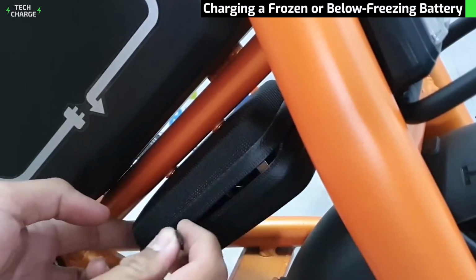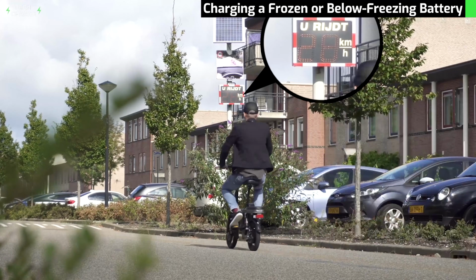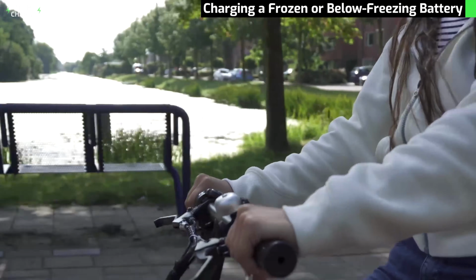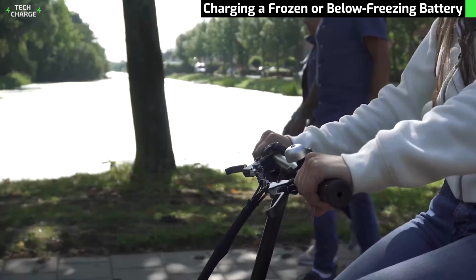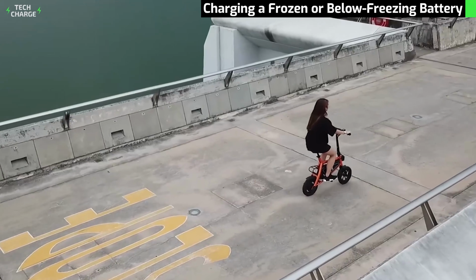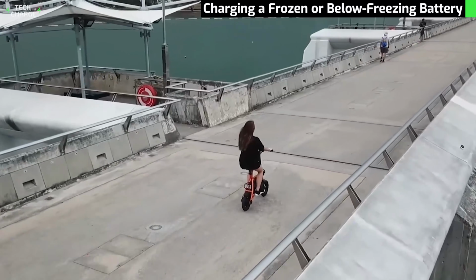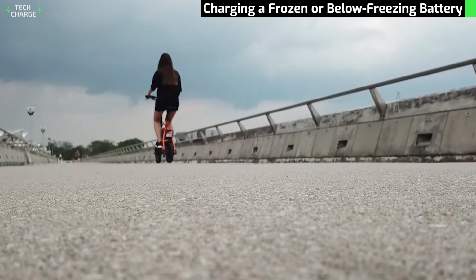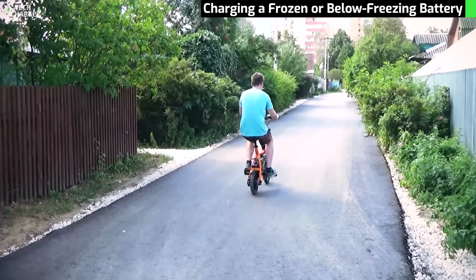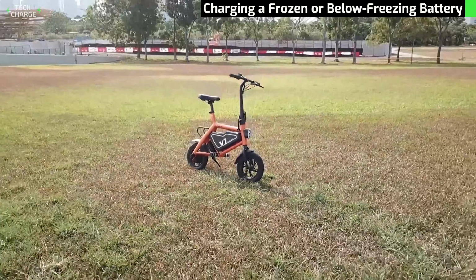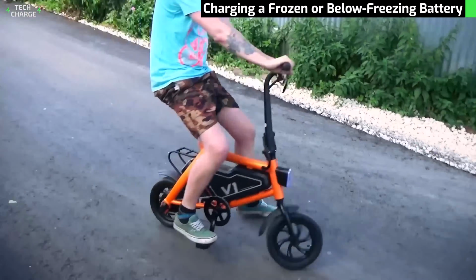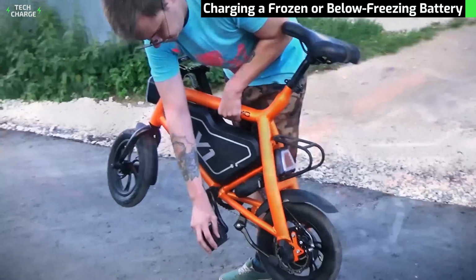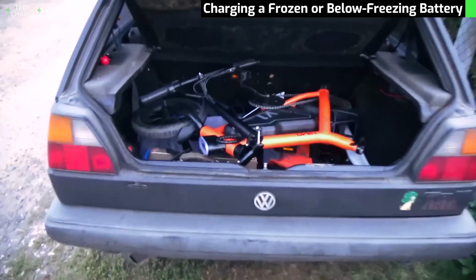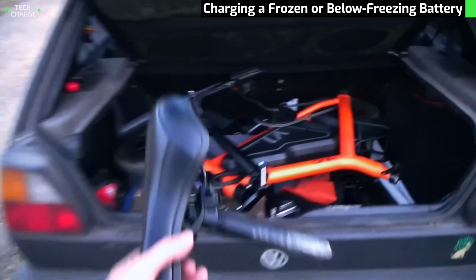The mechanism matters here because it explains why quality chargers won't charge cold batteries. When lithium ions move during charging at freezing temps, the sluggish electrolyte can't transport them efficiently into the graphite anode structure. Instead of intercalating properly between the graphite layers, lithium metal plates out on the anode surface. These metallic deposits reduce the cell's lithium inventory permanently, cutting capacity.